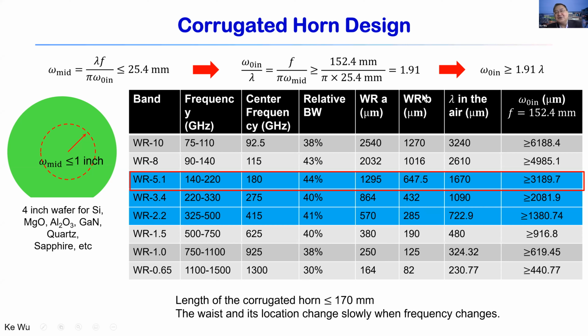But first of all, we need to determine the beam width we want to achieve. For example, we want a larger section with a beam diameter of 25.4 millimeters. In this case, we can calculate the input, which means the beam width generated by this corrugated horn. The corrugated horn gives a value of about 1.91 lambda, so this has to be satisfied during the design of the corrugated horn. That is the value we have to get. This formula tells right away the story of this geometrical dimension design.